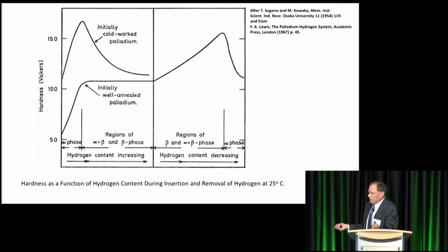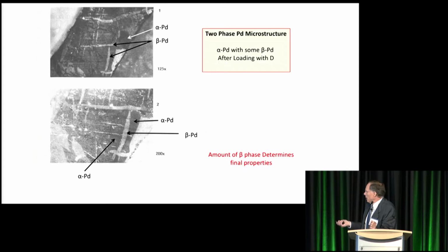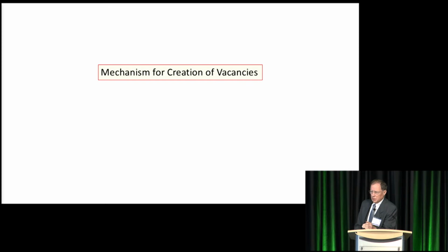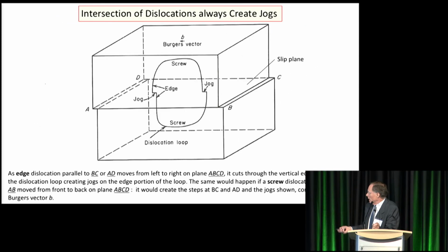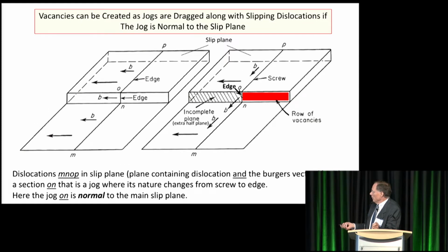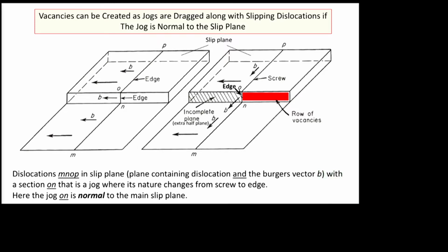I'm going to skip the dislocation mechanism that produces these large amounts of vacancies, but basically when you load and unload hydrogen, you end up with a dislocation structure that's very much like the plastically deformed or cold worked prior to initiating. So that would be the mechanism, which I'm going to have to skip. But basically, I want to just mention that when these dislocations intersect, if you have a screw with an edge component as a jog and it intersects another dislocation, it leaves a row